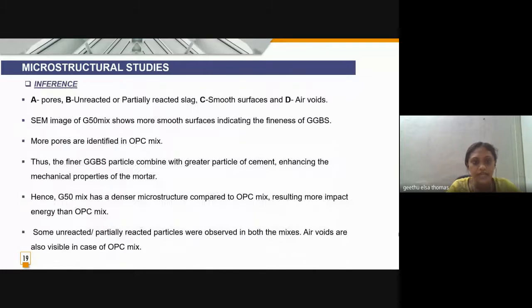It is observed that the SEM image for the G50 mix shows more smooth surfaces, indicating the fineness of GGBS. More pores are identified in the OPC mix. Thus, the finer GGBS particles combined with the cement particles enhance the mechanical properties of the mortar. Also, the G50 mix has a denser microstructure compared to the OPC mix, resulting in more impact energy than the OPC mix. Some unreacted, partially reacted particles were also observed in both mixes, and air voids are also visible in the case of the OPC mix.